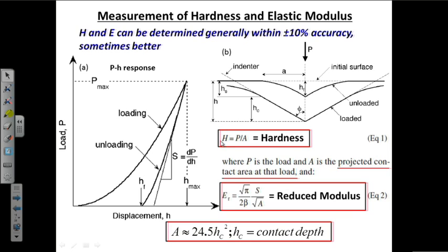It is important to note that both the hardness and reduced modulus can be calculated only if we know the projected contact area at that load. It turns out that the projected contact area is a function of the contact depth as defined previously. The formula is A equals 24.5 Hc square. So when we make the indent, we want to measure this contact depth, and if we know the contact depth, we can easily calculate the projected contact area that can be used to calculate the hardness and reduced modulus.